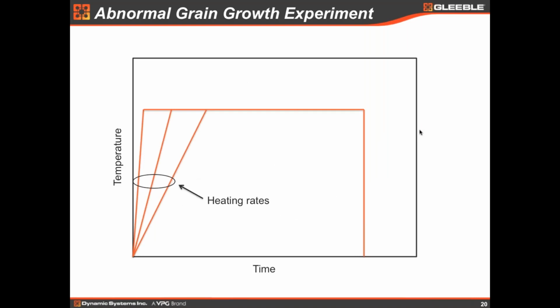So how can we study that? Well, of course, we have to study case by case why the abnormal grain growth is happening. But usually it's associated with high heating rates, because in high heating rates, you have a higher probability to have this partial dissolution of precipitates in certain areas, and then this will generate the abnormal grain growth. So we can check. You can go to higher and higher heating rates. As you may know, Gleeble can go to 10,000 degrees C per second. This is the maximum we can go, and we can see how these high heating rates can trigger the abnormal grain growth. So we test the different heating rates and check what happens. So this is another example.